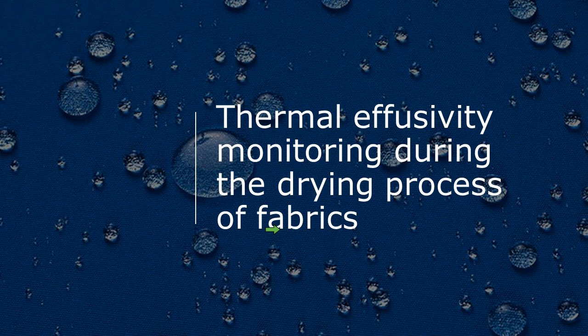But when we test a wetted material, that moisture is such a high effusivity. It's 1600 relative to a base starting point, usually in the range of about 100 to 400 units of effusivity. So you see this really steep, often starting effusivity, and then over time what you'll usually see is a decreasing effect.